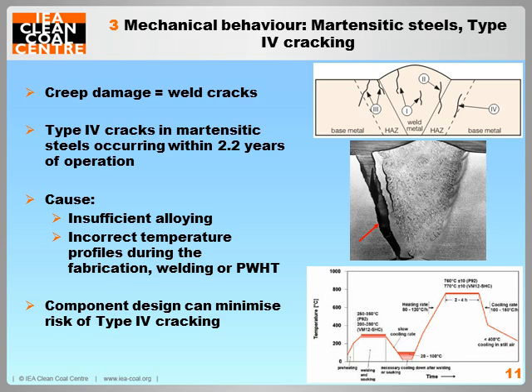Evaluation has shown the cause to be insufficient alloying or incorrect temperature profiles during the fabrication of the parent material, or insufficient alloying or incorrect temperature profiles of the weld material and the heat treatment procedures during the welding procedure. New components have reduced the risk of type 4 cracking through component design, which minimises stress in the weld, and so that the welding procedure and post-weld heat treatment procedures are easier to carry out correctly. Also, it has to be ensured that the parent material has the correct amount of alloying and is fabricated correctly.